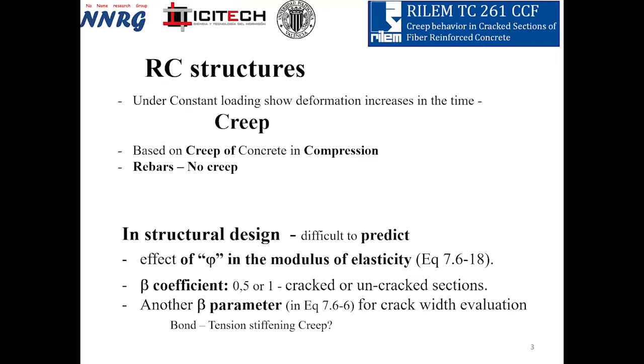Well, starting on reinforced concrete, when we talk on creep, we are always thinking that creep depends on the delayed deformation in the concrete because of compression. And we usually consider that rebars do not creep. And for the structural design, and that is not too clear to predict even in traditional reinforced concrete, we usually affect the modulus of elasticity by a creep coefficient that changes the deformation over time. And also we can apply some beta coefficient thinking on if the section is cracked or not, or other parameters related with evaluation of the cracks.